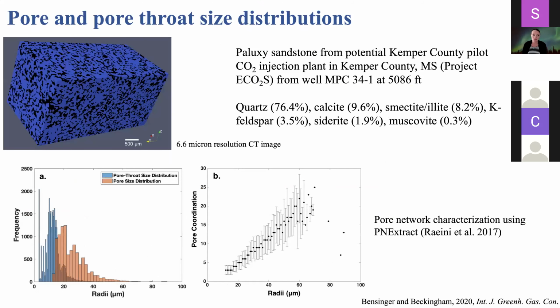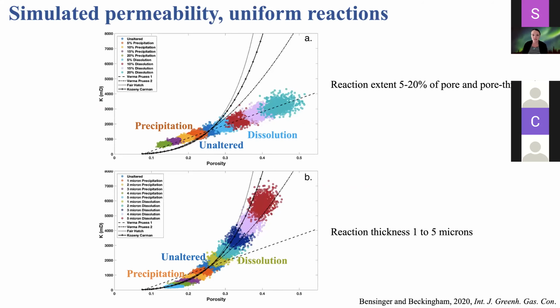We're going to use the same sample as with the last work I talked to you about, the Paluxy sandstone from Kemper County. Here we used CT imaging to understand the pore structure, where we can get the pore and throat size distribution, as well as pore coordination or connectivity, where you see an increase in coordination with pore size. Then we use that to construct our model. What we have done is run 1,000 simulations for each sub-scenario. If we look at the initial or unaltered permeability, this is using the pore and throat size distributions and connectivity that we initially measured, and we have 1,000 simulations, and you're seeing the resulting porosity and permeability for those simulations.